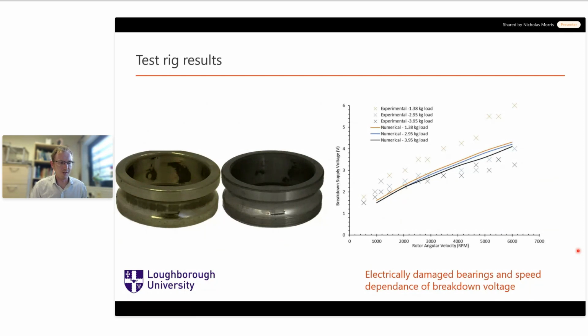So I think it was alluded to earlier, but there's standards for measuring the dielectric strengths of lubricants. Now, these are measured with the electrode distance at 1 inch separation. However, the distance between the rolling elements and the races within these bearings is sub-micrometer, at the most several micrometers. So we've got orders of magnitude difference in terms of the standard test for dielectric strength.